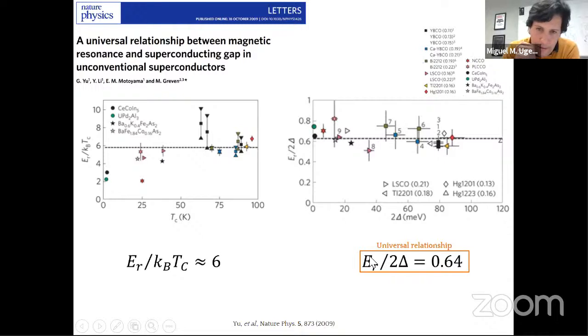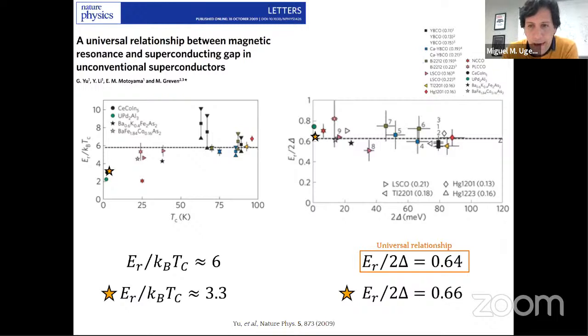So the energy, this E_R, it's also omega. So they follow this particular number. So we put the ratio that we found in our experiment, and it's basically exactly the same. It's 0.66. So it's quite close to the universal relationship that is expected for unconventional superconductors. So this gives us a first indication that this could actually be spin resonances.